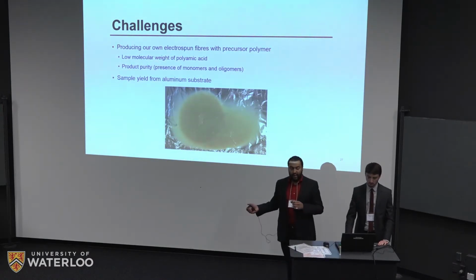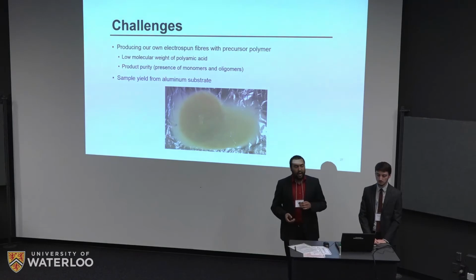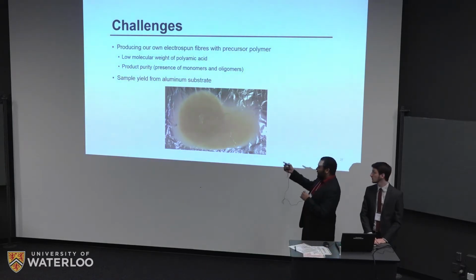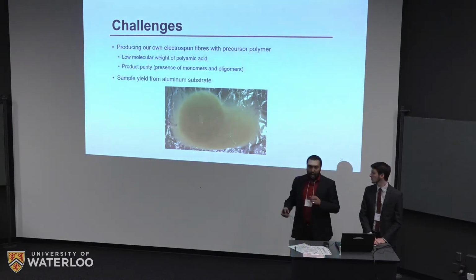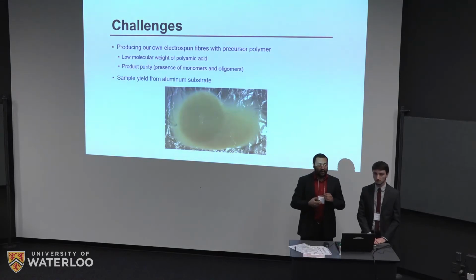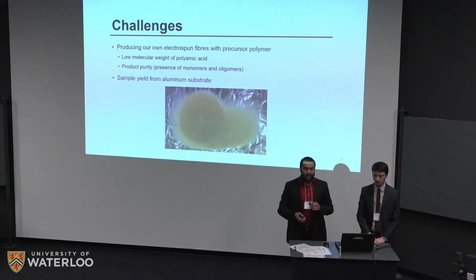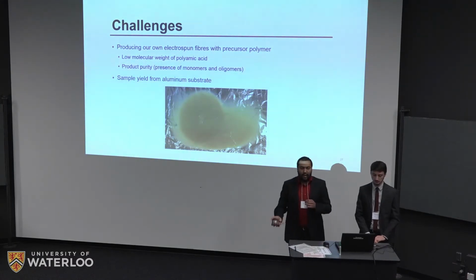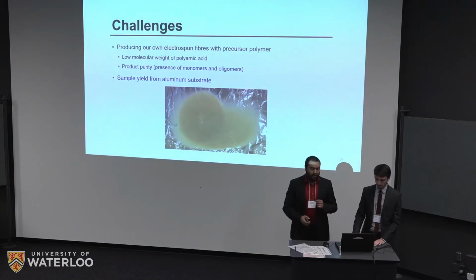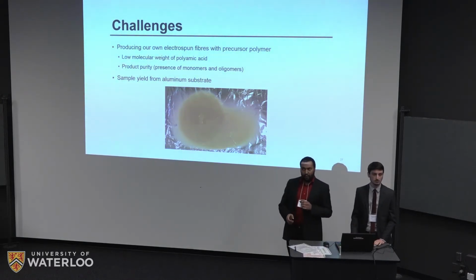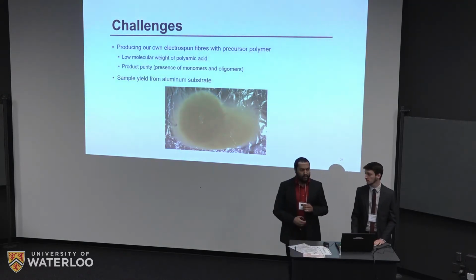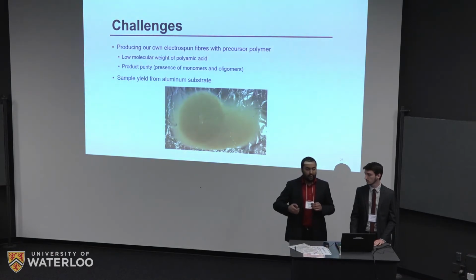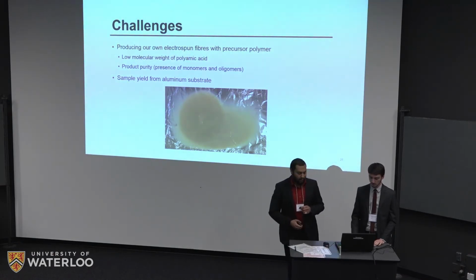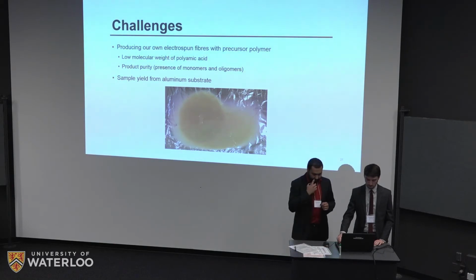And then additionally, the sample yield from the aluminum substrate. This is an example of one of our samples. What we ended up with was sort of like a coating. And so in order to run the characterization, especially for TGA, but also for DSC or any other characterization method, we need to have a non-negligible amount of material, obviously. And so we were able to get about 3 to 4 milligrams off for most of our TGA samples, which was good, but it was something that we really had to look into later on in our project.